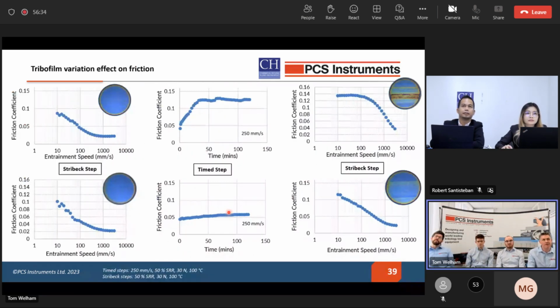I'm going to go through this very quickly. I'm going to skip quite a lot of this because I'm conscious of time, but it illustrates here how tribofilm formation really can affect the level of friction in the contact. Starting here with 2 different tests. This is our baseline Stribeck step, showing how friction varies with speed. We then do a long period of running, so 120 minutes of running in using a time step. We're measuring friction throughout this, and we can see how the friction changes differently between the oil here on top and the oil here on the bottom. And then when we take another Stribeck step at the end of the test, and we look at the difference, and we also take a Slim image at the end of the test, just seeing how different the behaviour, the friction in the contact, is now.